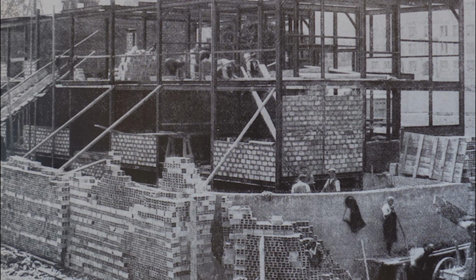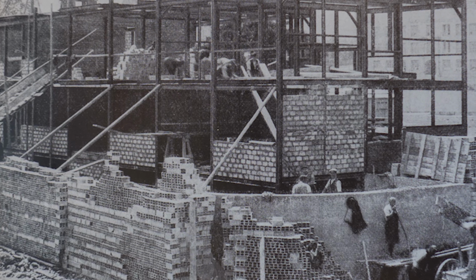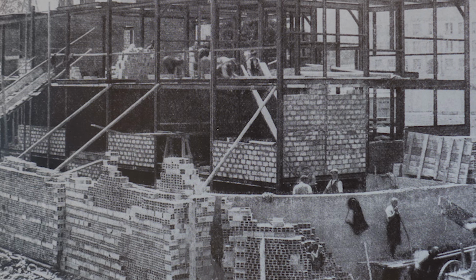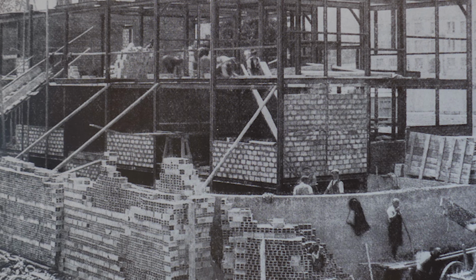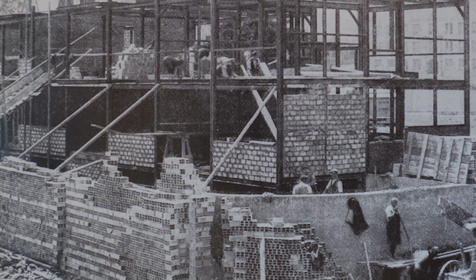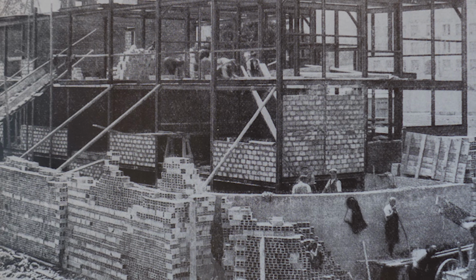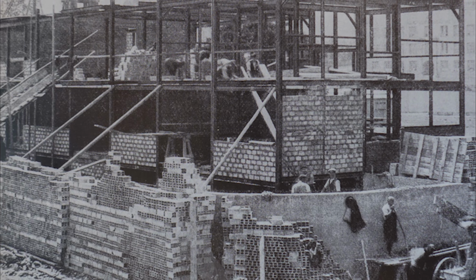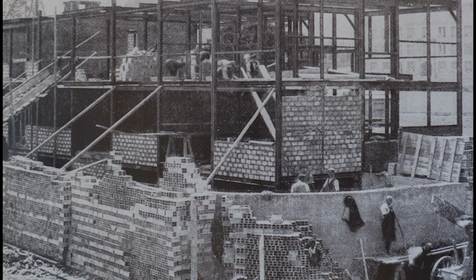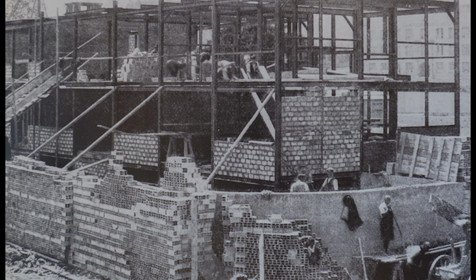limits. Humphrey's ongoing testing revealed that the Ingalls Building concrete continued gaining strength years after construction, with core samples taken in 1908 showing compressive strength exceeding 6,000 pounds per square inch compared to the 4,500 pounds measured during initial testing.